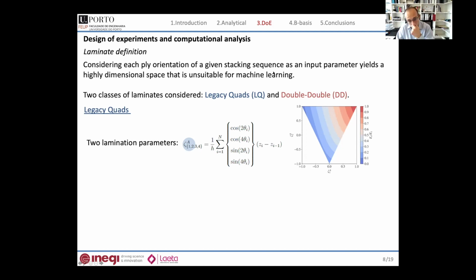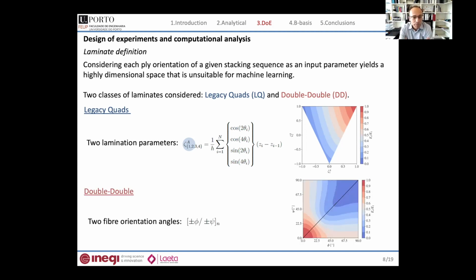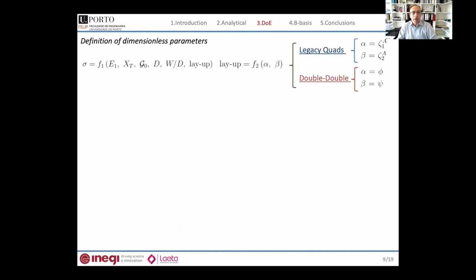So the other thing that we have to take into account is if we plot the normalized Young's modulus with respect to the two lamination parameters, we can see that they are not independent. So we have a region of feasible layups that we need to account for in the sampling process. So if we use the double-double, again, we just have two fiber orientation angles to define our laminate. And again, if we relate the normalized Young's modulus with now the two fiber orientation angles, we can see that our space is symmetric with respect to this diagonal line. So here we have to take into account restrictions, and here we can take advantage of this symmetry.